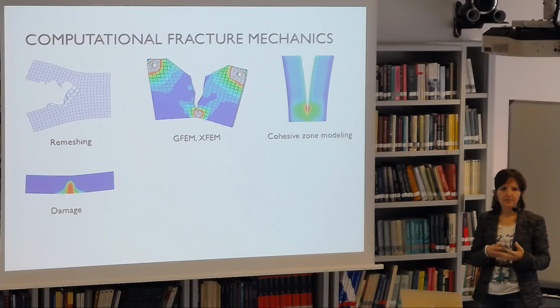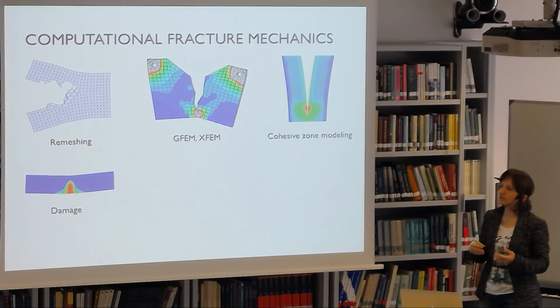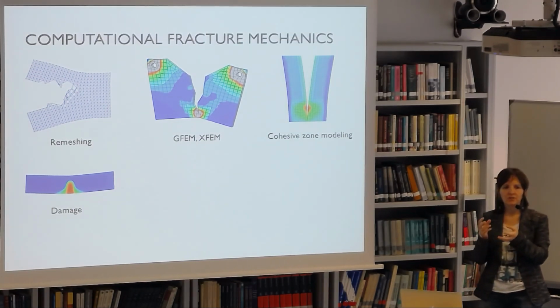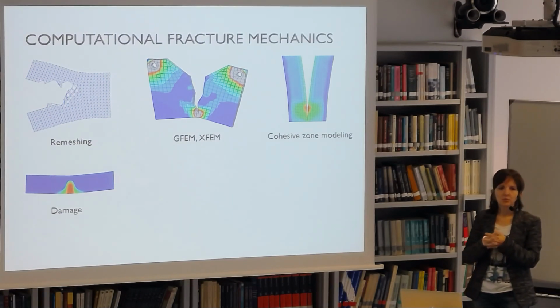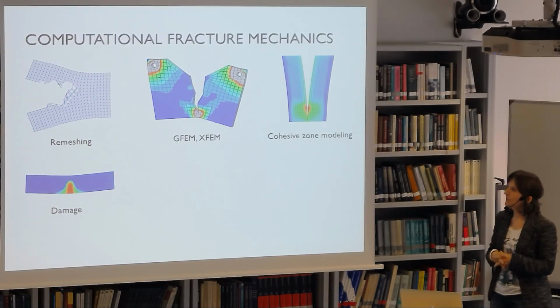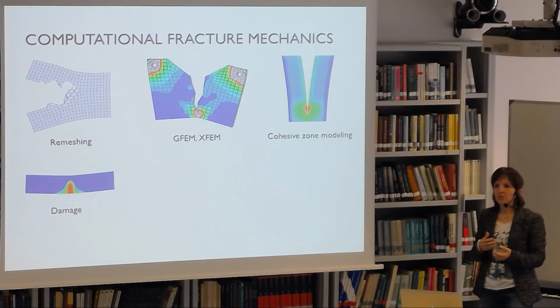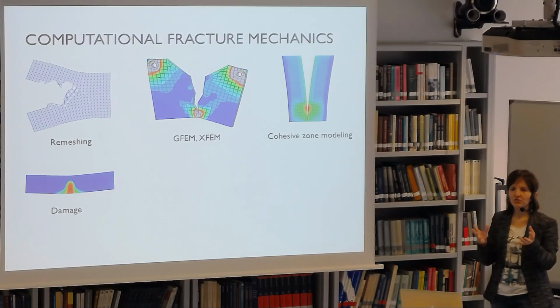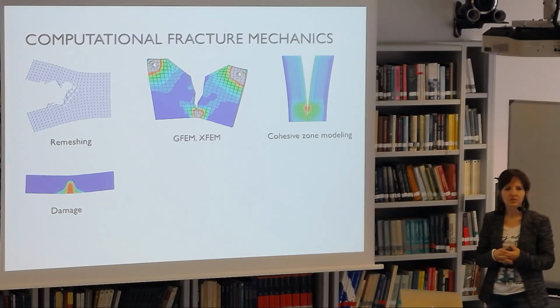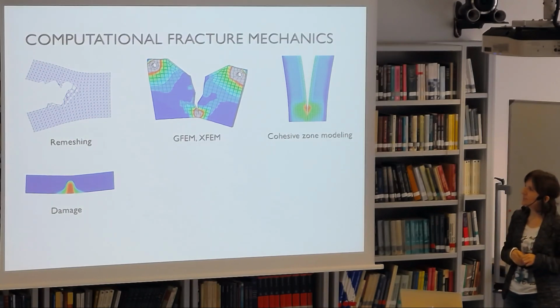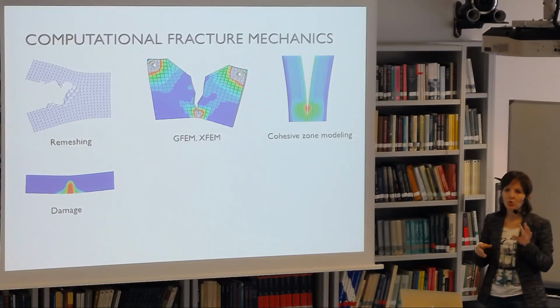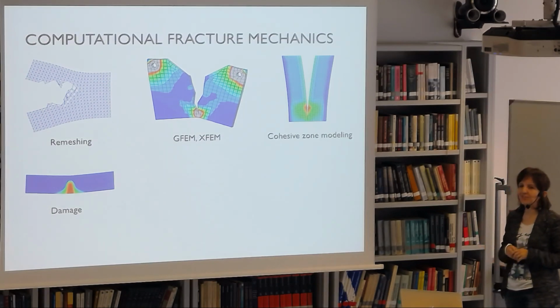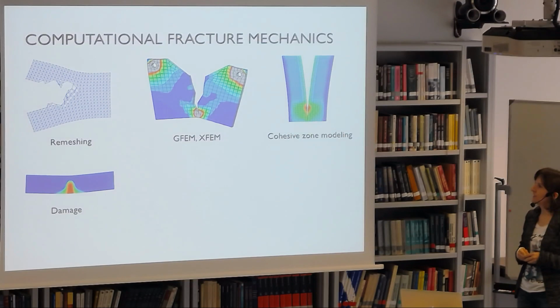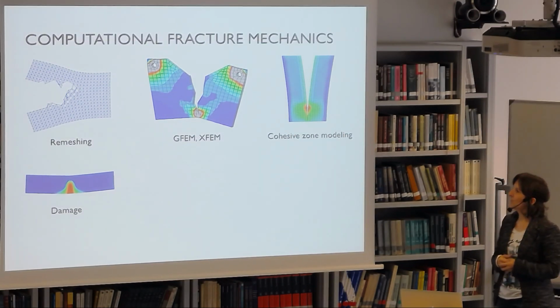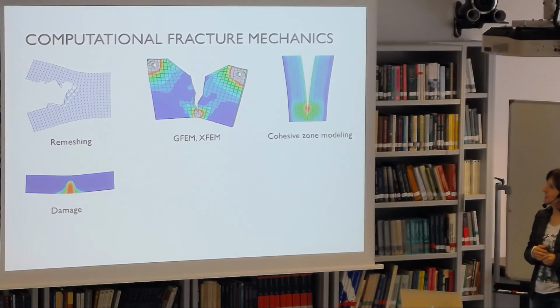GFEM, XFEM, so generalized finite elements or extended finite elements, are also a quite popular choice. In this case, you don't need the crack to go between elements. You can have enrichment within one element. You can allow for jumps in displacements. Also in this case, you need criteria pretty much for any complicated topology of cracking. If you want, again, branching or merging of cracks, you need ad hoc criteria for that. And also, if I may, integration and conditioning are big issues, and coding in 3D is very, very complicated. So I really wouldn't like to be the one coding this in 3D. There are people who do it, but it's not really something that one finds very comfortable, at least.